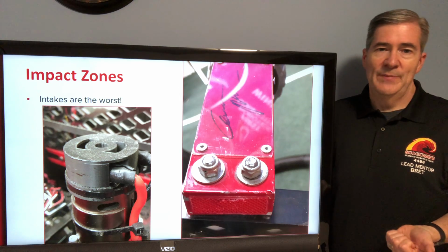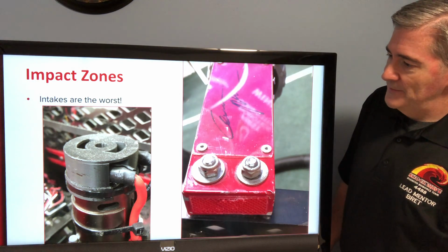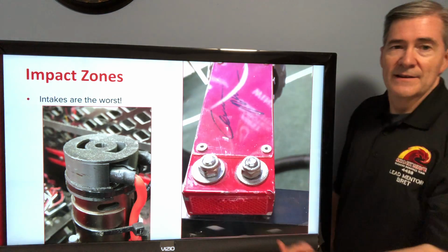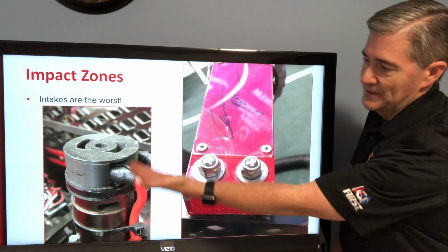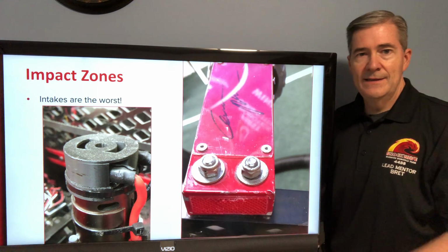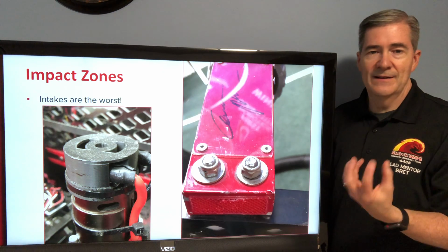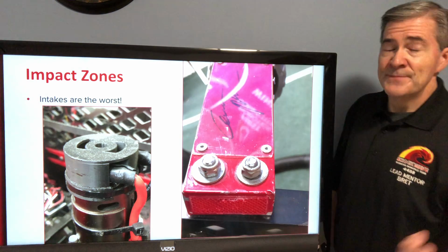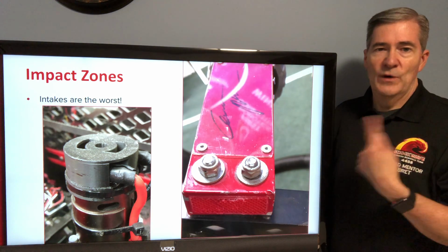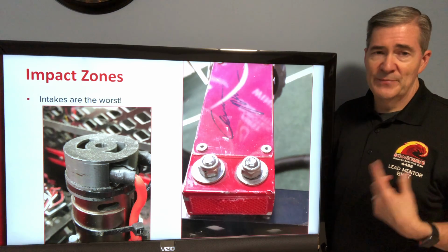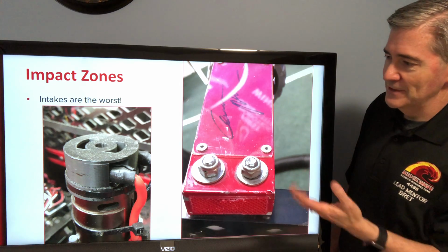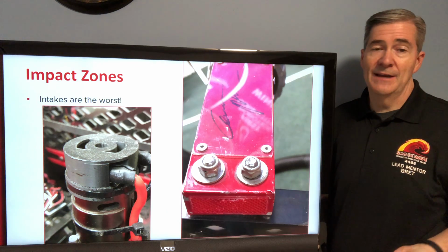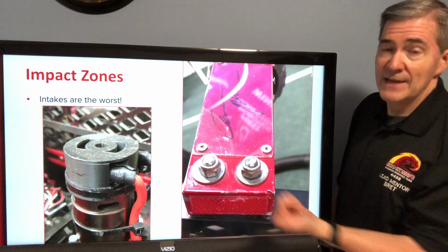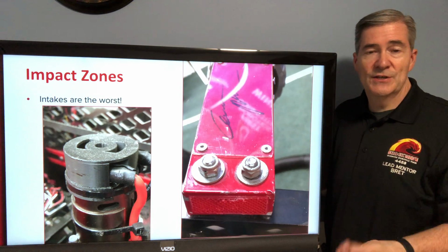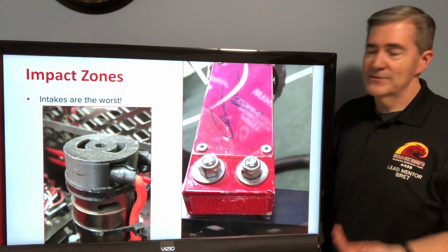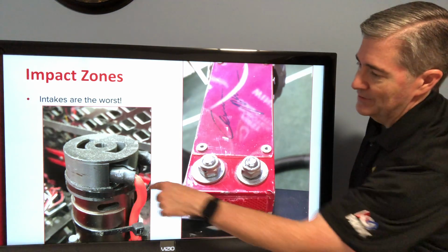Also, impact zones. So this is an example on an intake where we had these nice little bumpers to try to protect the end caps area of 775. We went through one of these things every match, maybe two of them per match, because they just were in such an impact zone. They just got hit all the time. And we were printing in PLA at the time, and while it's nice and strong, it doesn't have very good impact resistance, so they were just always cracking and breaking.